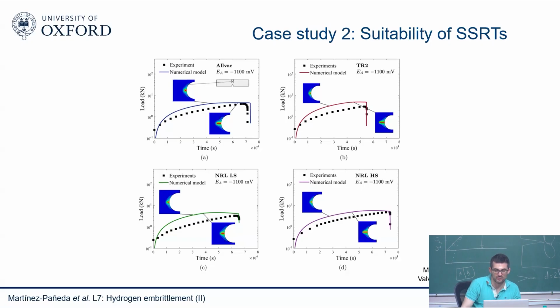So yeah, we basically think that this explains, it's a model. We don't have clear experimental evidence, although there's a group in Manchester that have shown, by comparing fracture surfaces and doing some interrupted testing, that indeed cracking initiates first. So it seems that what the model predicted is being confirmed later by experiments. So the model is telling us that most likely crack initiation occurs, and this explains the conundrum. This explains why hydrogen only enters a little bit, but brittle failure is seen over large distances. But this also tells you that this kind of approach is not a valid test. You need to do a proper fracture test.